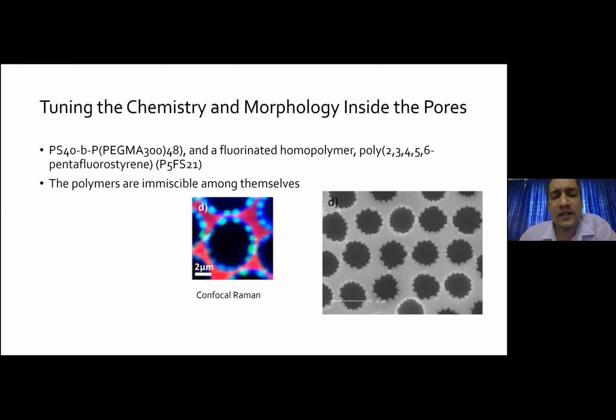So they used confocal Raman, which maps a particular frequency onto the surface by surface scanning, and these maps are reconstructed. This confocal Raman picture is a reconstructed picture from the independent wavelengths that were analyzed over the surface. What they found is that the perfluoro polymer is the one taking the rim inside the pore, whereas the other two polymers are taking the skeleton.